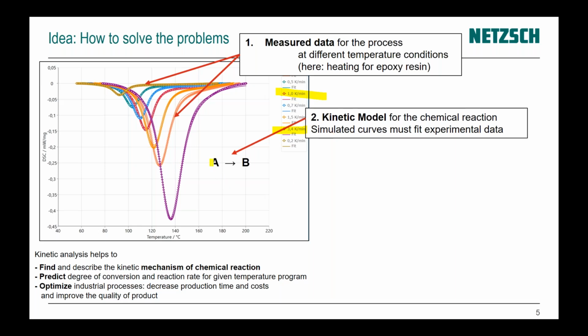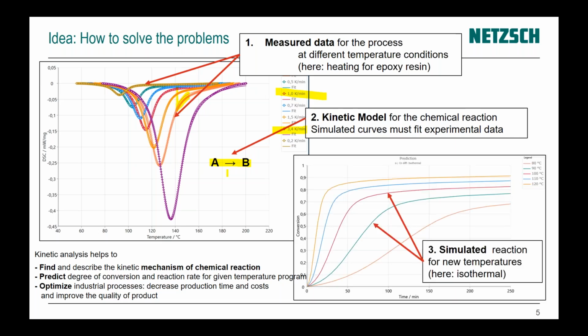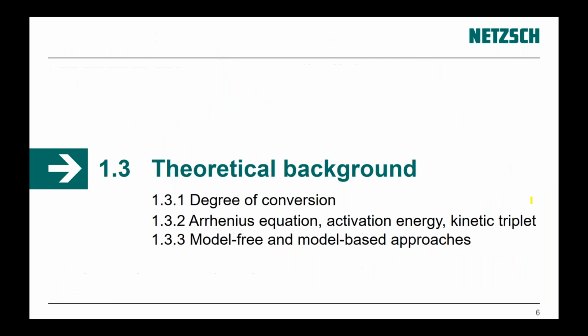Let's see if the calculation done with this model agrees with experiment everywhere, for all curves—then this model is correct. This means the model can be used for predictions at any temperature and any temperature profile, any heating rate. Now we can use this model for simulation: we can simulate DSC, degree of curing, degree of crystallization for any temperature profile, isothermal or complex.